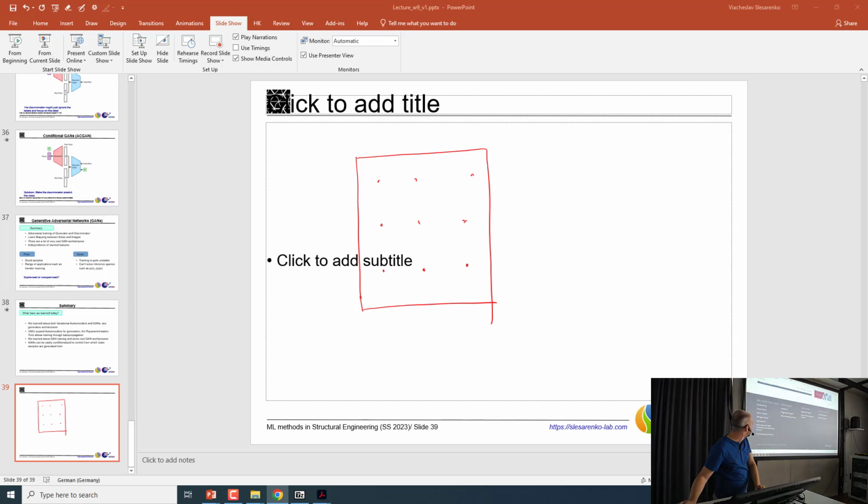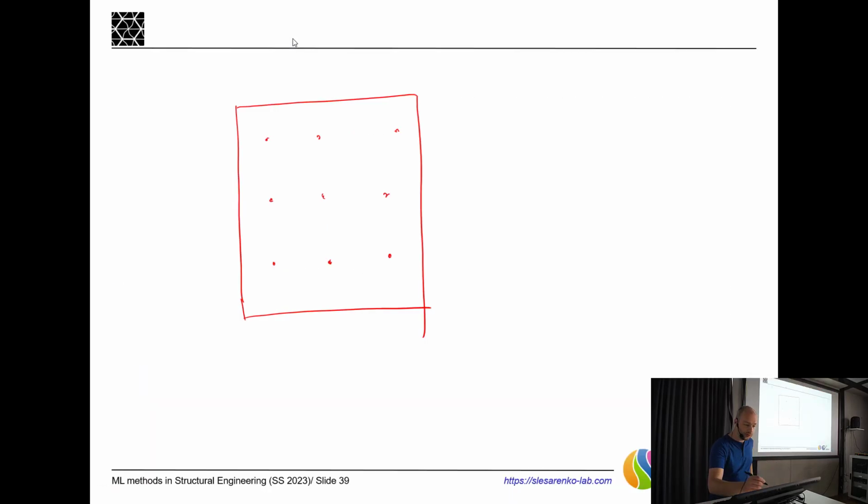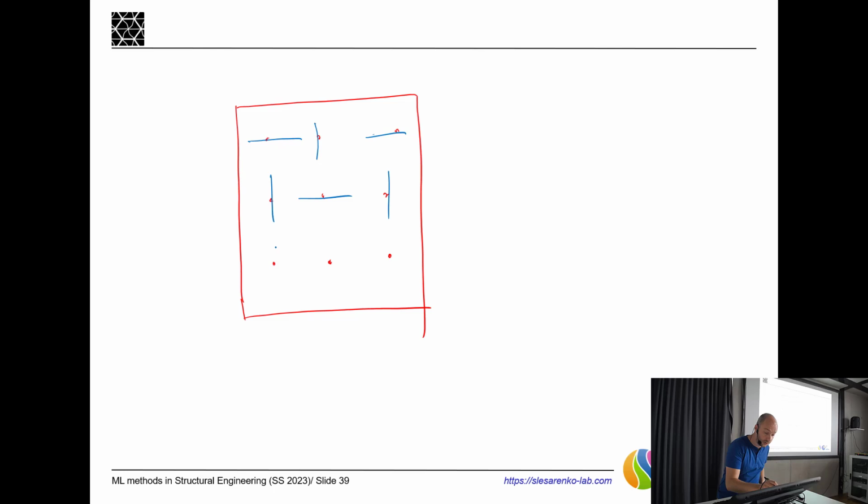I think maybe there is some example. It's in my paper, I think. Wow, you can see it here. So if you have a system with rotating squares, I can bring a sample next time, you have a Poisson ratio of -1. Let me go back to the presentation. Basically, what you can do with the cuts is take them and arrange them in this alternating pattern. And in this case, you will have something very close to -1 in Poisson ratio.